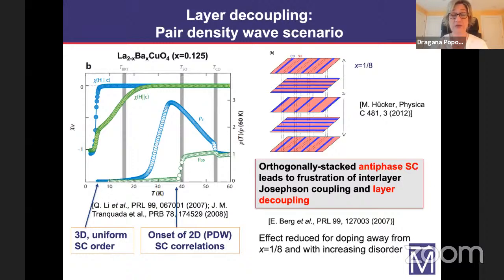There have been many other experiments done on this material, and it is now generally agreed and accepted that this initial drop of the in-plane resistivity corresponds to the onset of superconducting correlations in the planes. So in these striped cuprates, stripes are actually rotated by 90 degrees from plane to plane. So in this paper, they show that the presence of a pair density wave in such an orthogonally stacked striped system leads to the frustration of the interlayer Josephson coupling and therefore to the layer decoupling. So the experiments were consistent with this picture.